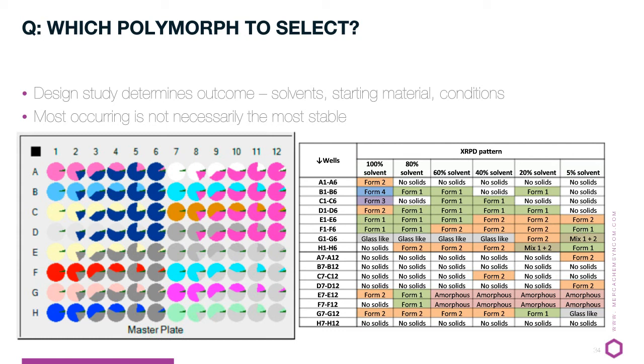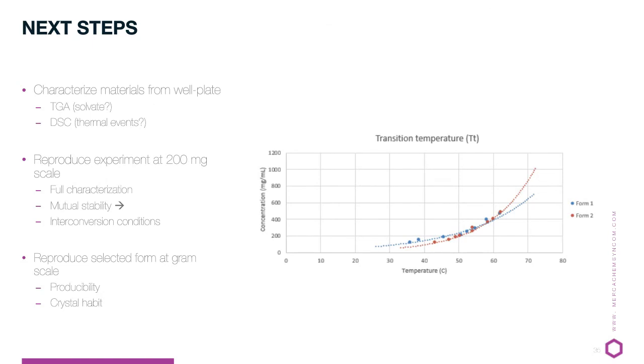In this case, it's the master plate, the different conditions, and we have an overview of the X-ray patterns found. This design resulted in 4 different crystalline forms, and it was clear that form 3 and form 4, these are solvent dependent. Only in one pure solvent these were obtained. But by looking at the results of form 1 and form 2, it shows to be completely random. Well, just a screenshot of the forms, that is not a conclusion. It is the dataset for the next steps.